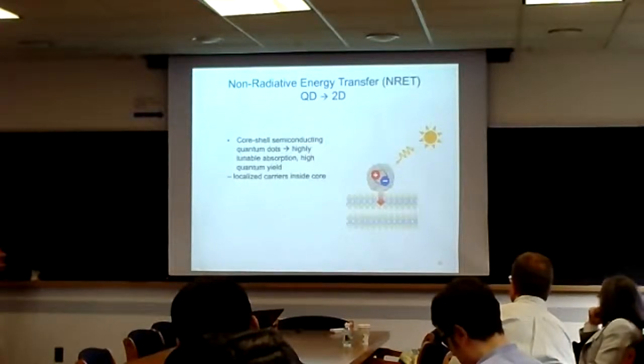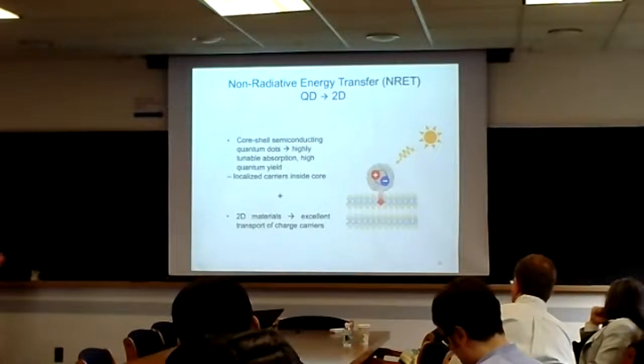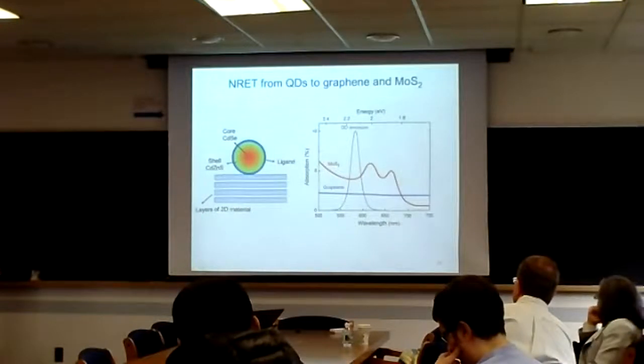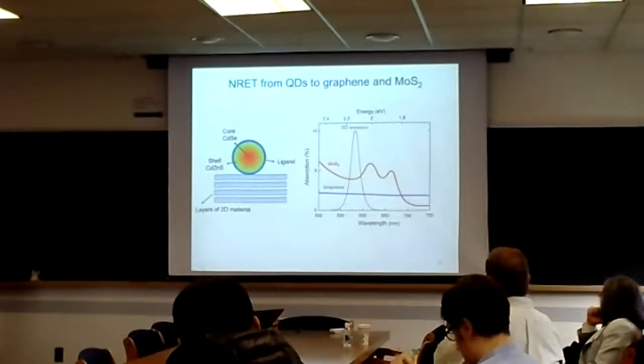When I started looking at these materials, the question was how you can extract this excitation energy from the quantum dot to the outside. You can think of charge transfer, but that would be very inefficient with a very thick shell and exponential current. One way to do it is non-radiative energy transfer using dipole-dipole interaction. And we had 2D materials lying around, so why not couple it to these? We had a quantum dot emitting at around 2.1 eV, and this is the absorption of a monolayer of MoS2 and graphene.